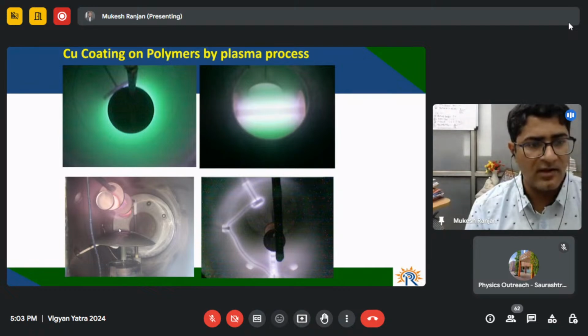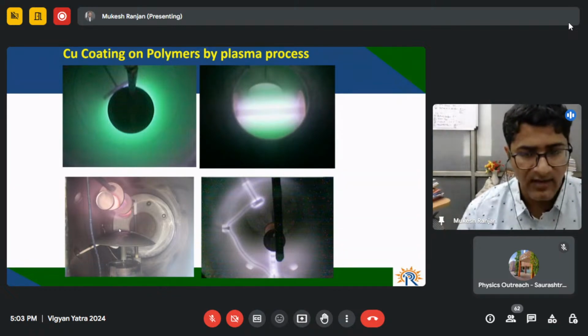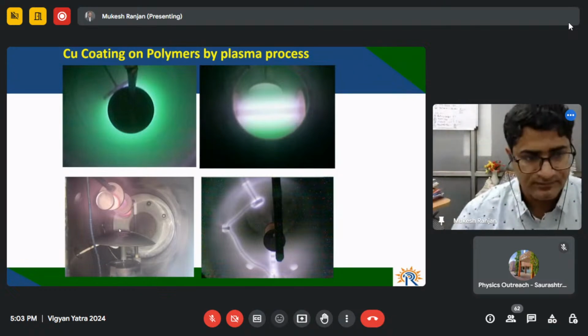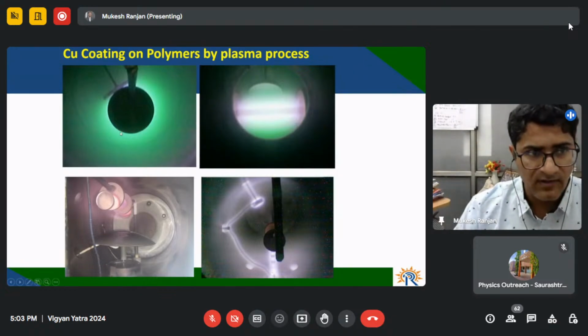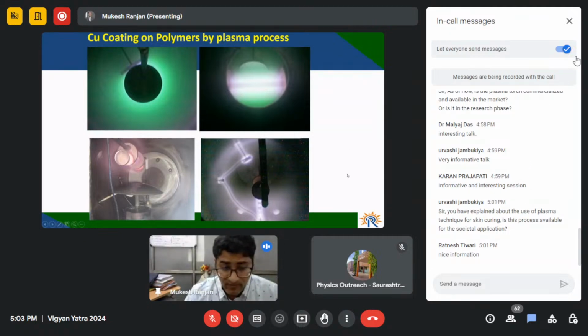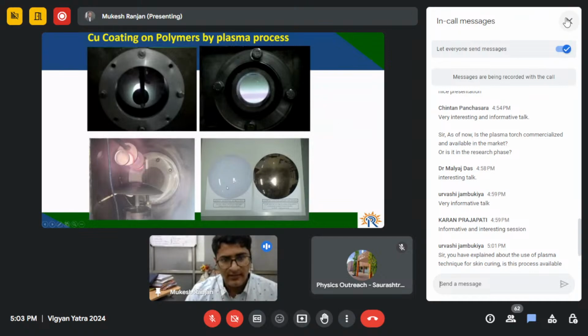So we developed it, but the requirement was to have a coating over a large area, like 20 centimeters, 30 centimeters, 1 meter. So we indigenously developed a plasma-based sputtering system for them so that it can coat homogeneously over the polymer surface. Coating a polymer surface is not as straightforward as other coatings. First the surface has to be cleaned by the plasma process, and then the sputtered material has to deposit on the surface. So we successfully developed this flexible antenna for SAC Ahmedabad. This is the polymer surface uncoated, and the second one is the coated one.